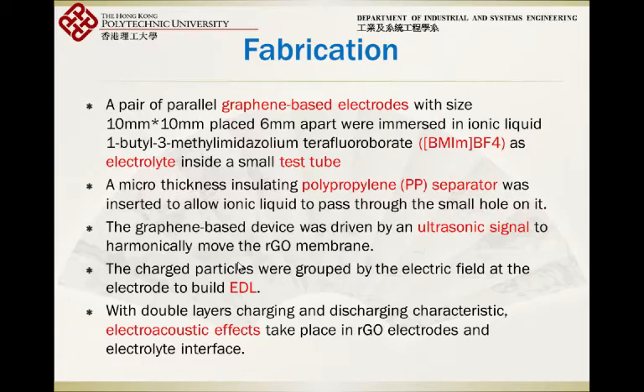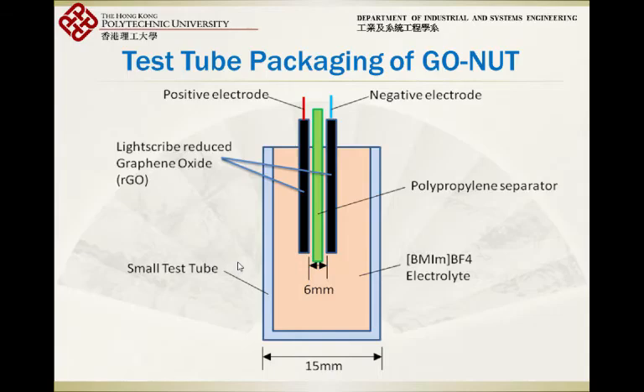And after the making of the electrode, you need to do the packaging. The packaging, all you need to do is to use a membrane to separate the two electrodes, and you also need to coat electrolyte to provide the electric double layer to the electrode. So this is the packaging. We have two electrodes, and you have a membrane to prevent these two electrodes from getting in touch. And then this is the electrolyte we use.